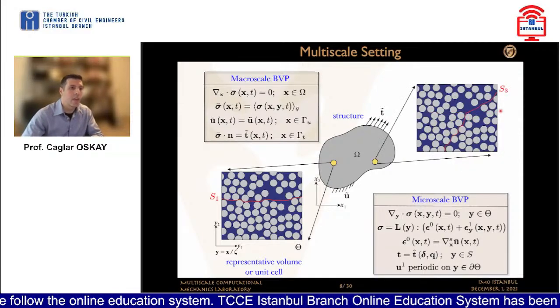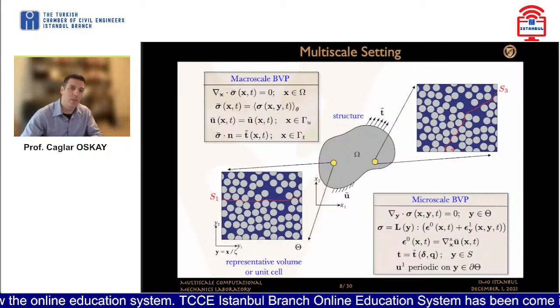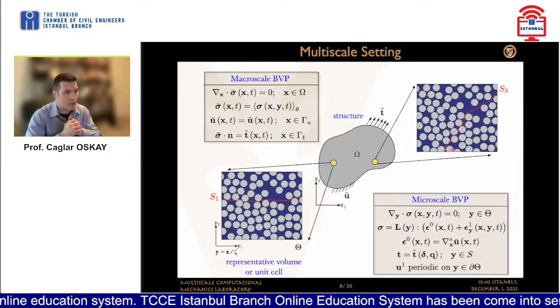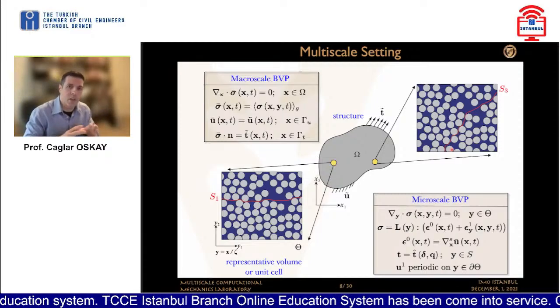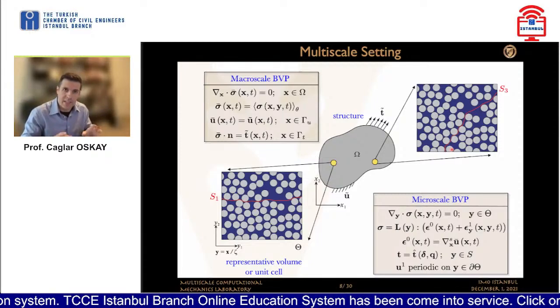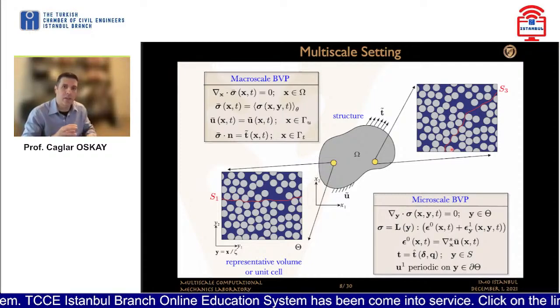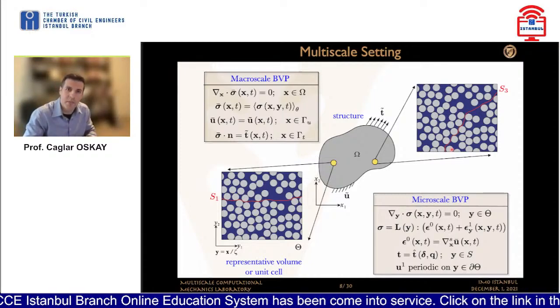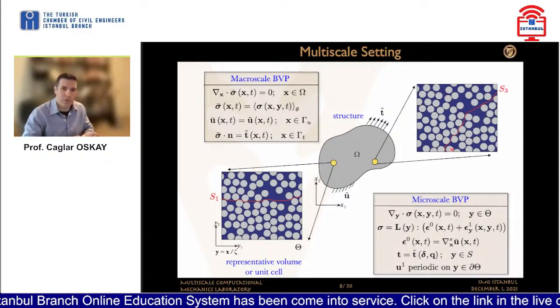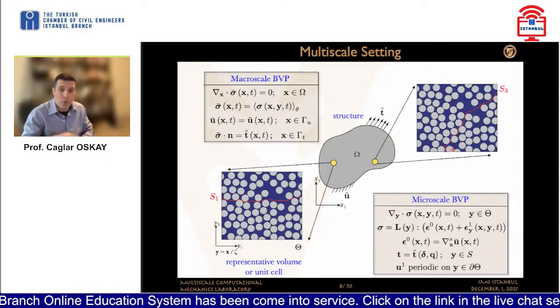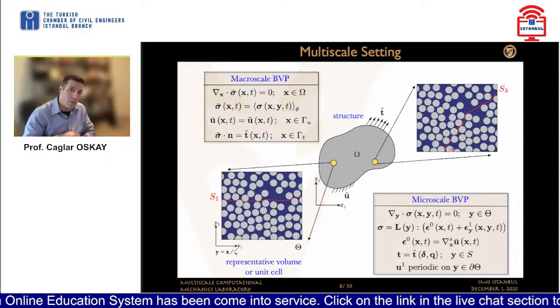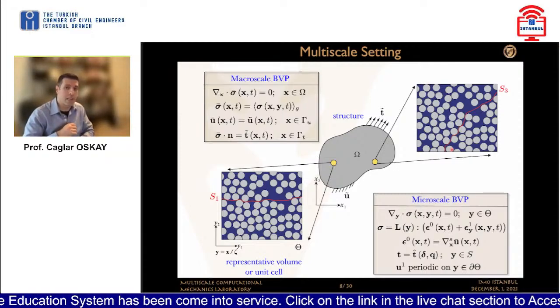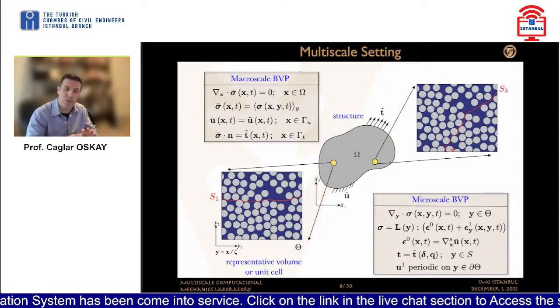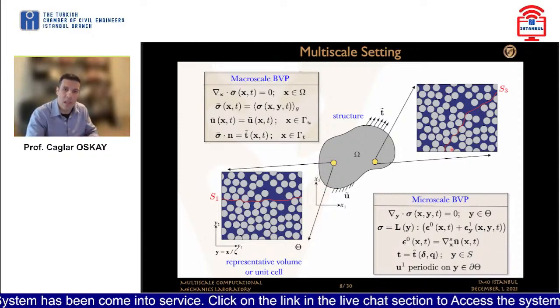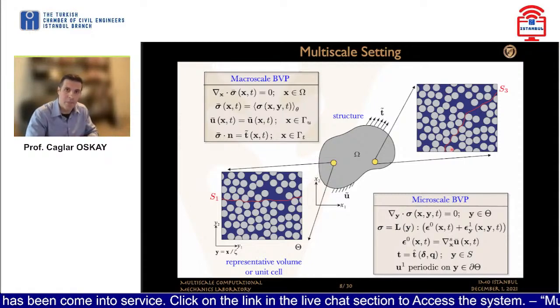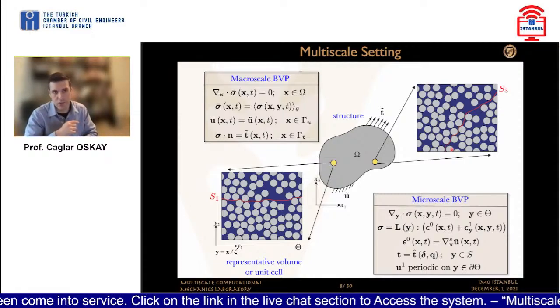Continue to load it. At another point, you have a different crack with a different orientation, for instance. So if you consider this to be a completely random microstructure, then depending on the loading condition and the position, there are an infinite number of possibilities of where these cracks occur. We will talk about that too in a minute. But fortunately for us, for long fiber-reinforced composites, there are certain orientations and crack features that are more likely to occur and more likely to happen, which is information that we would like to use